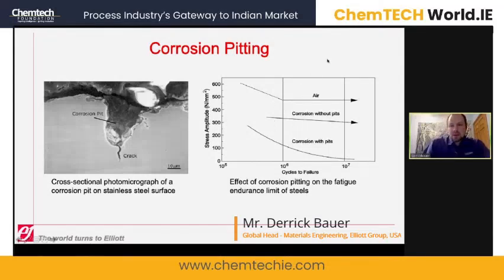The graph on the right is showing the fatigue endurance limit of materials, and rotating equipment is under cyclic loads with each revolution, and you can see that the fatigue endurance limit on a corroded surface with corrosion pits can be 4 to 5 times lower than the expected endurance limit in just a standard air environment. So this has a potential to significantly reduce the life of a hydrogen recycle compressor and cause premature shutdowns.